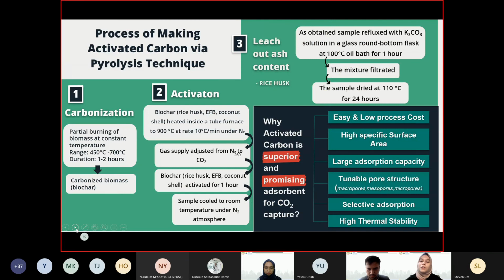Now, let's talk about synthesizing AC through pyrolysis techniques from agriculture waste. This technique has three stages, where the first stage is carbonization, activation, and the final stage, which is leaching out the ash content. In the first stage of the process, biomass is partially burned at constant temperature ranging from 450 to 700 degrees Celsius, for approximately 1 to 2 hours to be converted into biochar.